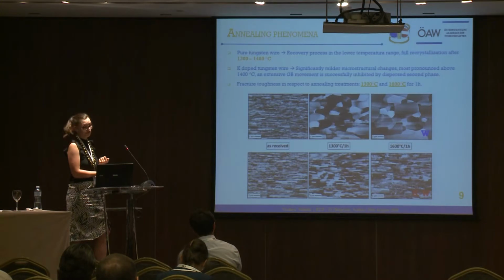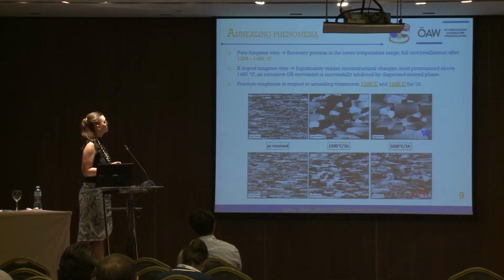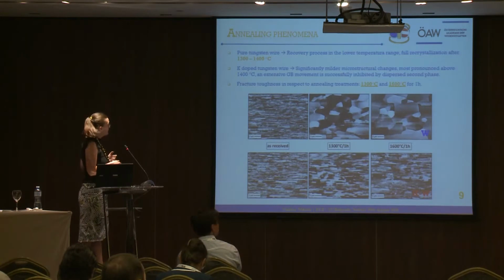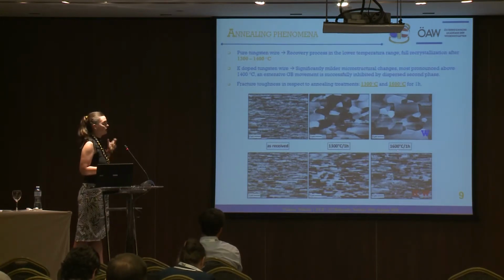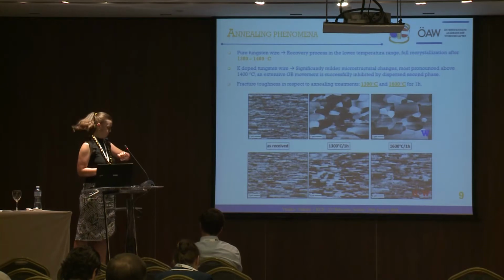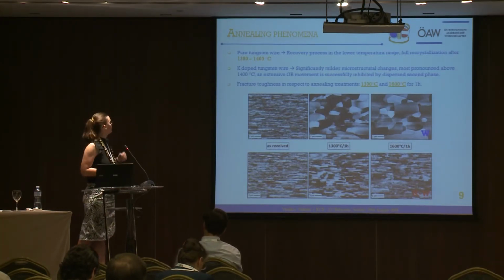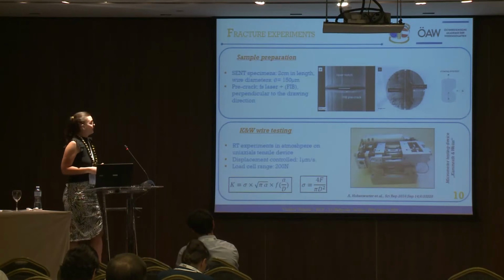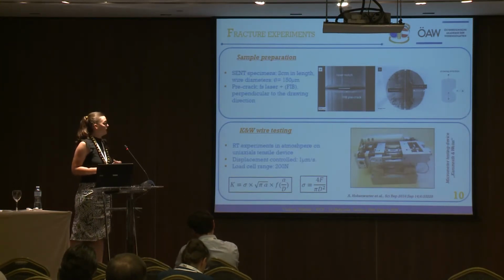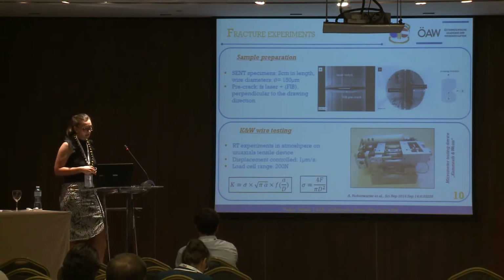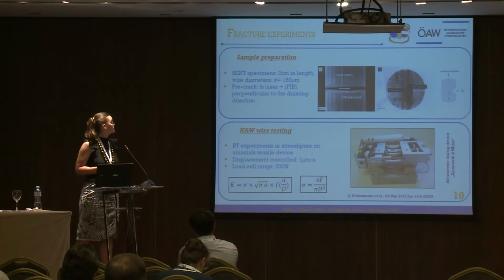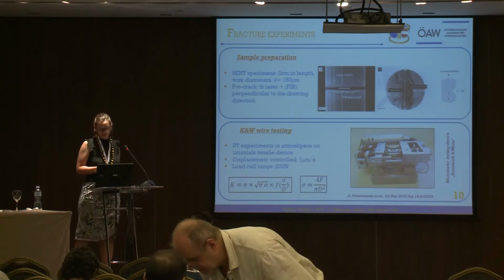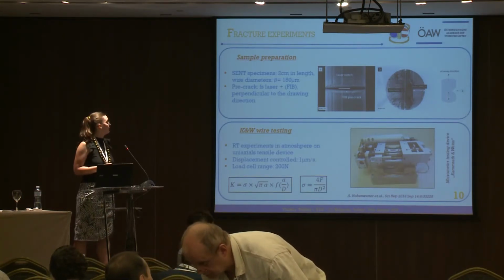And then the selection of our fracture samples was done. We wanted to look at fracture properties in the as received state, and 1300 and 1600 degrees C were chosen as two additional samples. Fracture experiments were done on a Kammrath and Weiss micrometer scale tensile device. Single edge notch tensile specimens were tested. Here you can see a little sketch. The pre-crack that we need to insert was made by femtosecond laser.